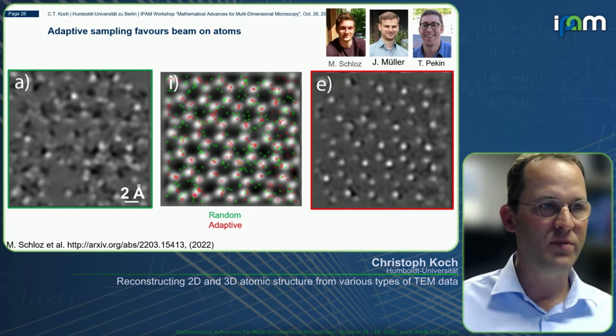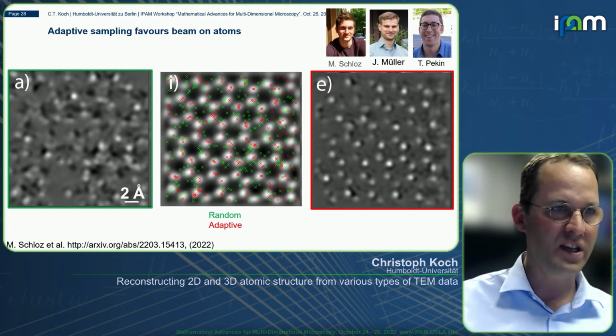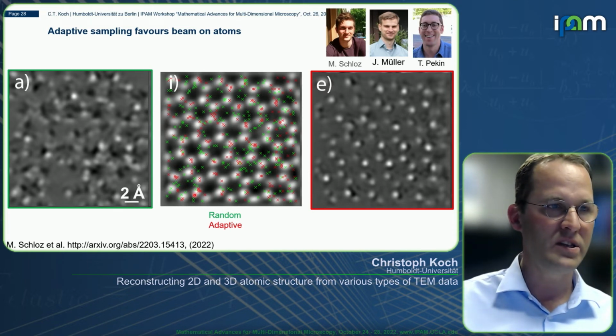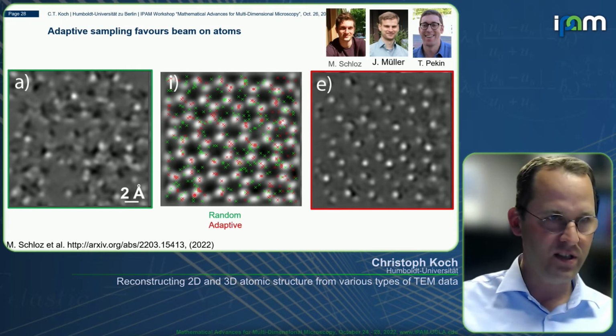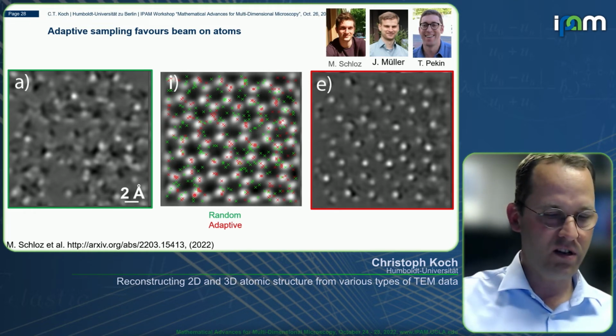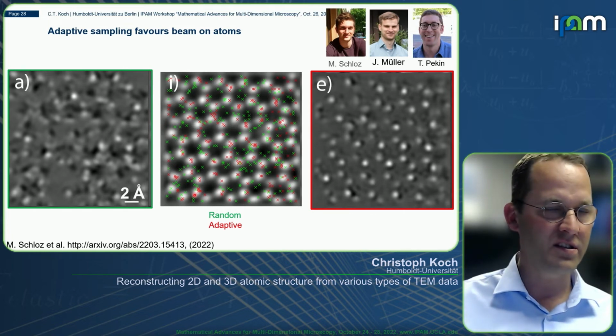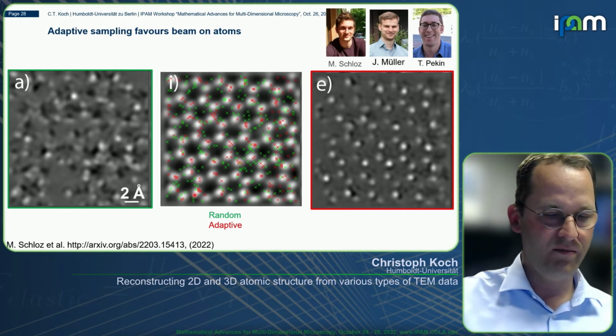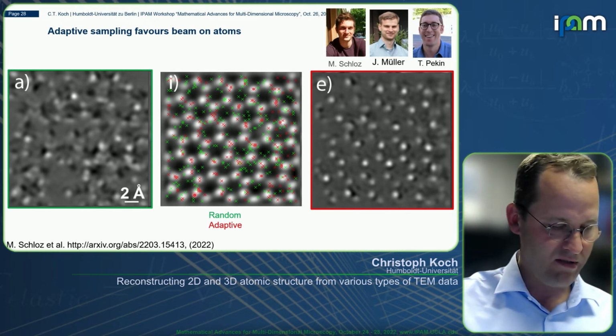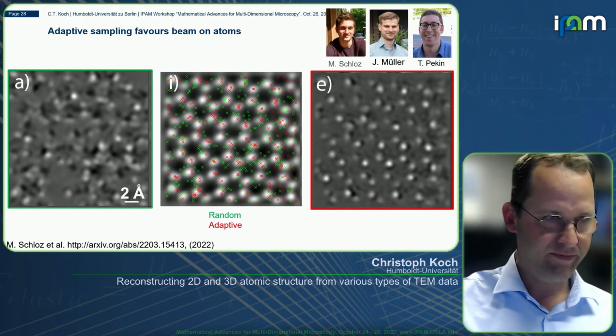So it really seems that if your beam is positioned on an atom, it produces, of course, stronger scattering and more information than if the beam is between the atoms for these 2D materials. I'm only talking about such a sample right now. And that is actually interesting because this could lead to a much simpler adaptive scanning scheme, if you think about it.